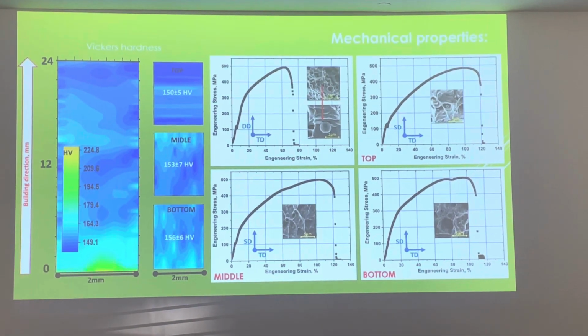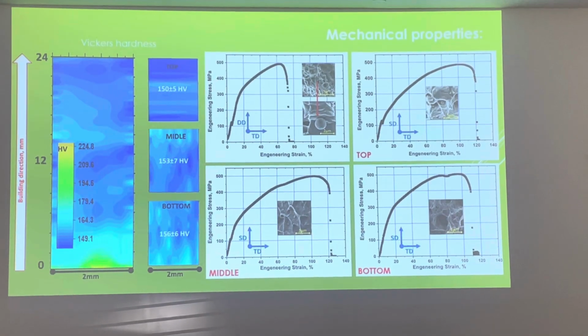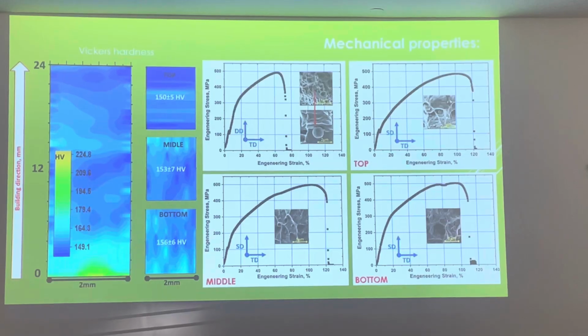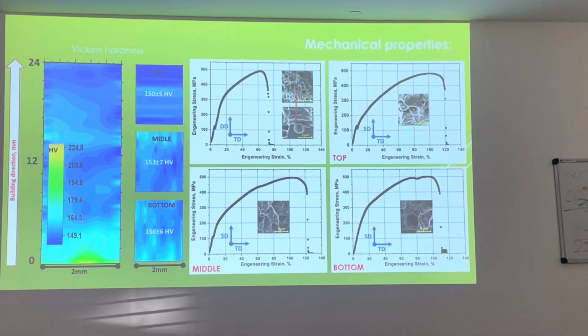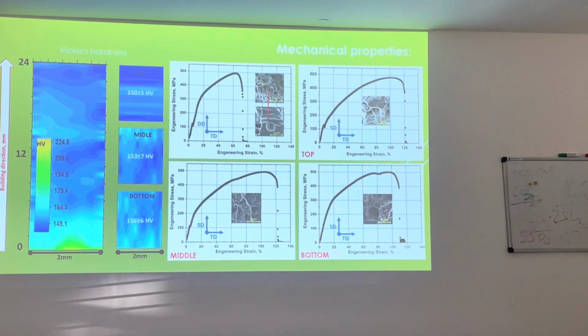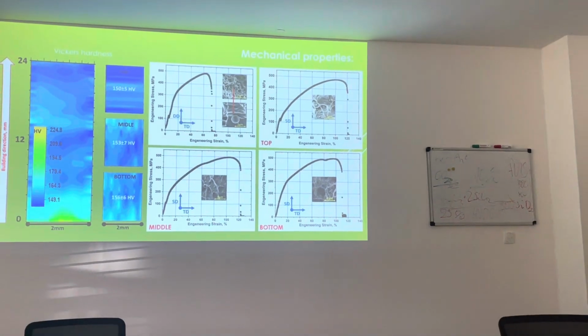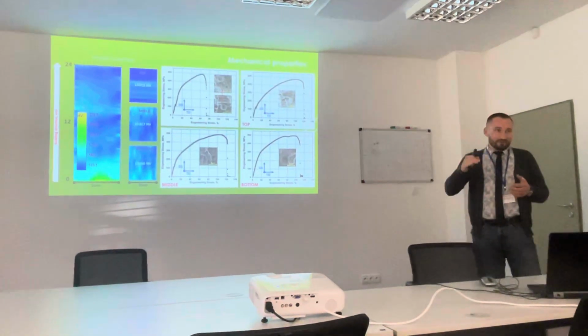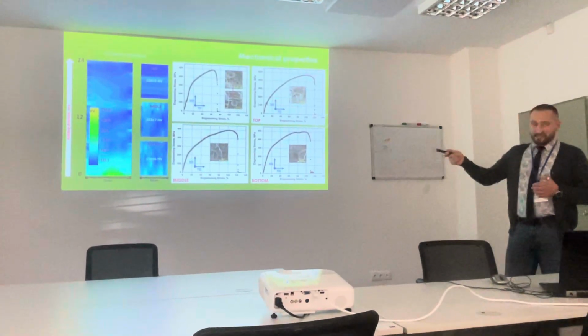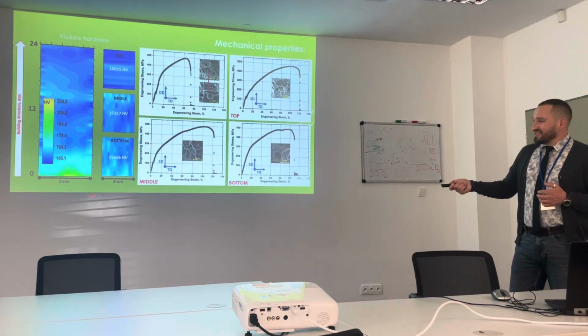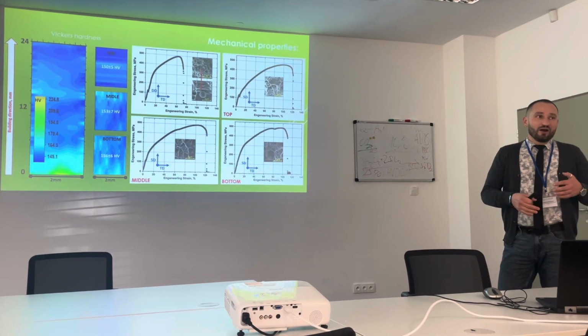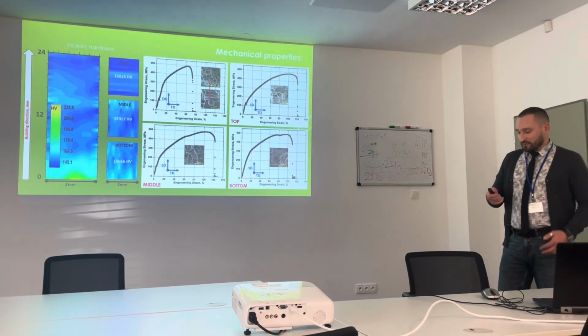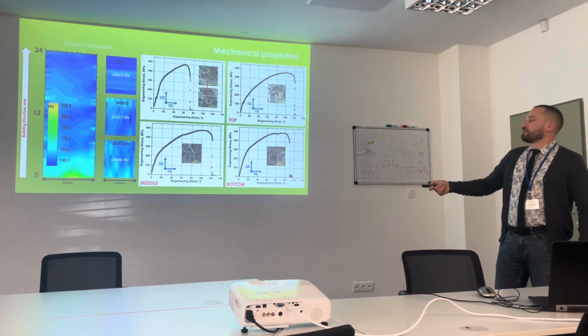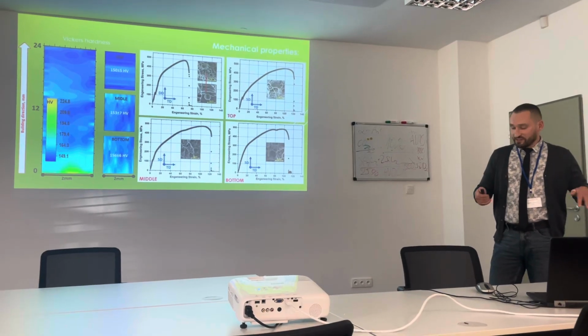Mechanical properties. Mechanical properties were analyzed from bottom to top and also in cross-section. We clearly see that we have more or less uniform distribution of mechanical properties. As I told you before, at the bottom part we have higher hardness and mechanical properties. This is connected firstly with grain size, and second, with a small mixture of deposited metal with substrate. So this could be called the buffer layer, which we eliminate from consideration.